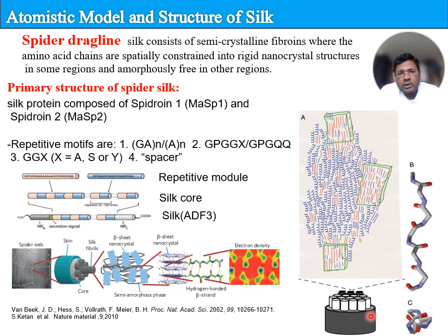The molecular structure here consists of beta-sheet regions containing alanine, the red lines here, and glycine, the blue lines, interleaved with predominantly 3-1 helical parts, which do not contain alanine. All chains tend to be parallel.